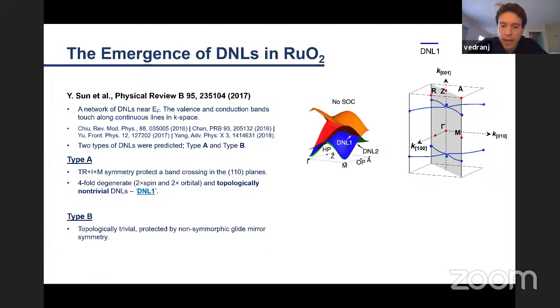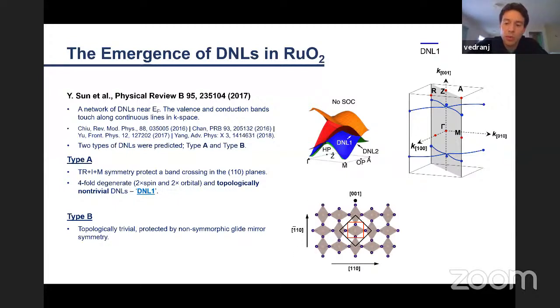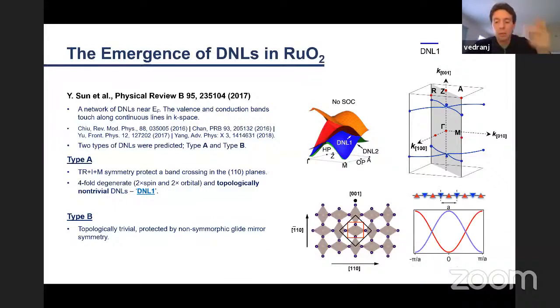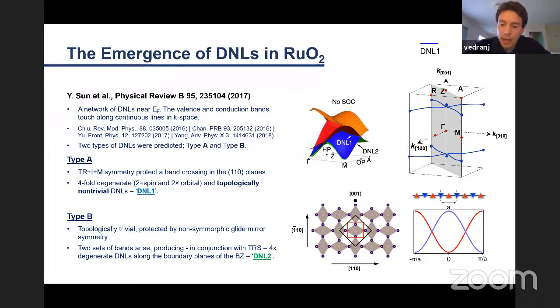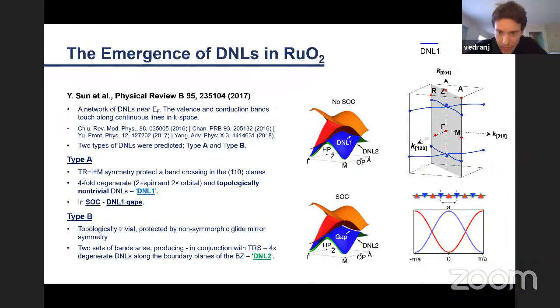And then there's the second type of Dirac nodal line in ruthenium dioxide. It's topologically trivial, protected by non-symmorphic glide and mirror symmetries. So ruthenium dioxide is essentially a bipartite composition of two sublattices within different ruthenium dioxide octahedra that are related by a fractional translation of half a body diagonal around the 110 plane. And in analogy with this diatomic chain model, this glide plane effectively doubles the unit cell, backfolds the bands, and then in conjunction with the symmetry properties, it forms a second set of Dirac nodal lines in the system, and they are along here in the Brillouin zone.